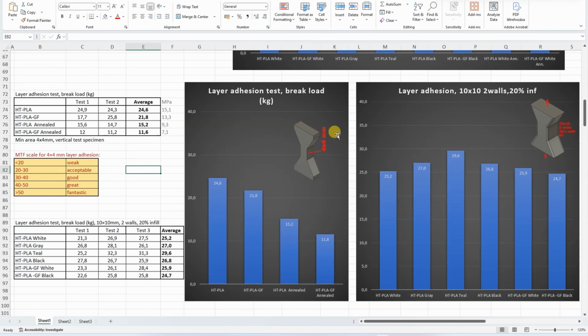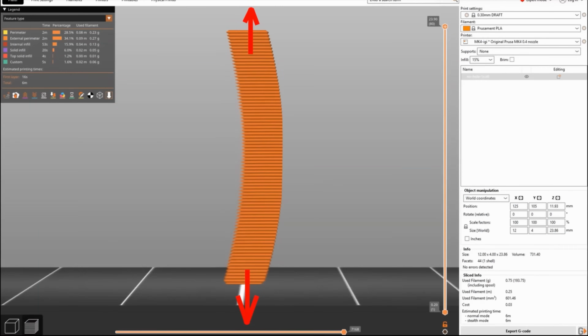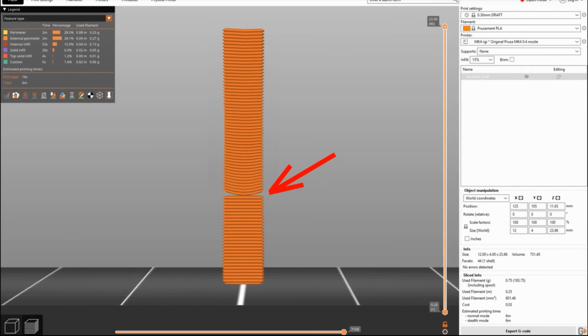On the first layer adhesion test, 4x4 mm solid inside, we can see that the HT-PLA and the glass fiber version have acceptable layer adhesion, but unfortunately after the annealing it was weak. Probably the reason for the weaker layer adhesion after annealing is micro warping, which will result in some delamination or maybe even add some bending if the object itself is warped during this test.